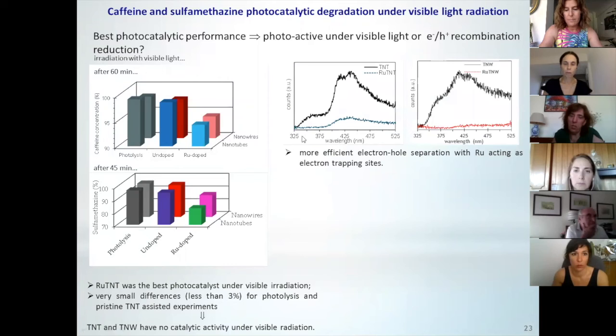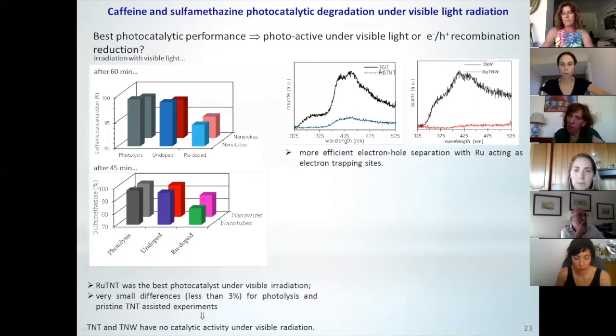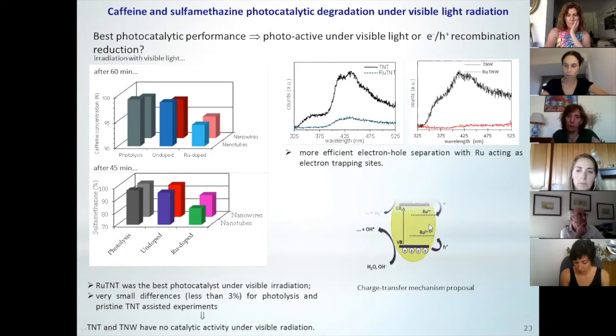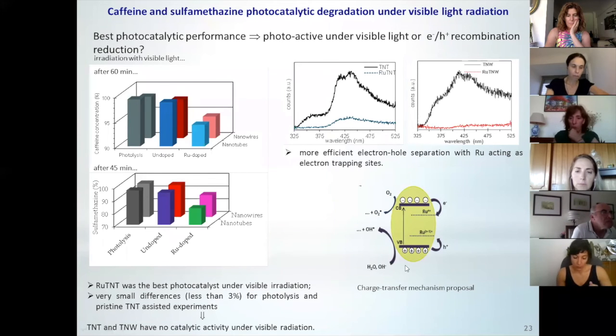About the recombination, these are the photoluminescence spectra, and as you can see, when we have the ruthenium in the system, we have a decrease in the emission intensity of these particles after irradiation. So with all this information, we were able to propose a mechanism of photoactivation of these materials, where we have the influence of the ruthenium ions here in the forbidden zone, and that improves a lot the photocatalytic performance of these materials.